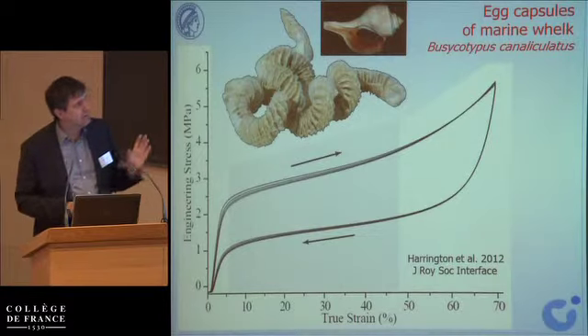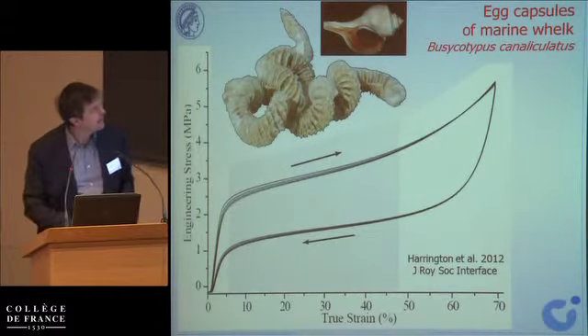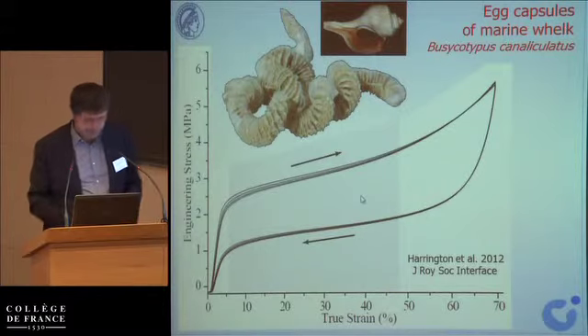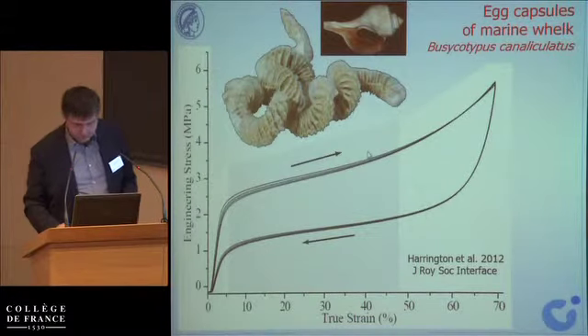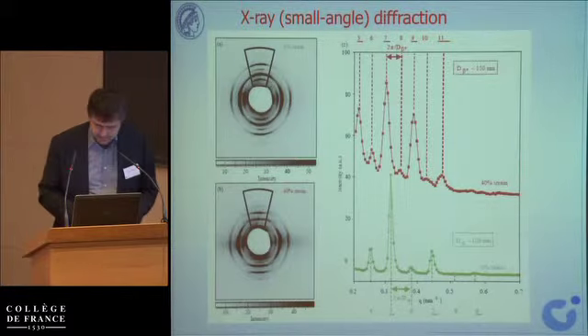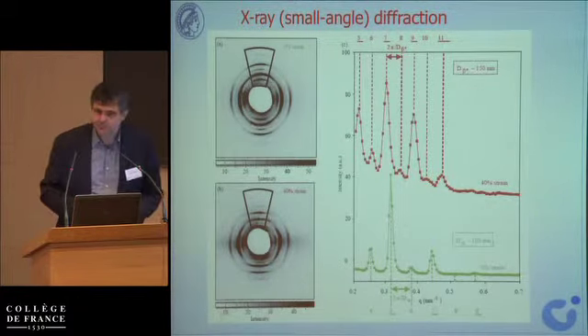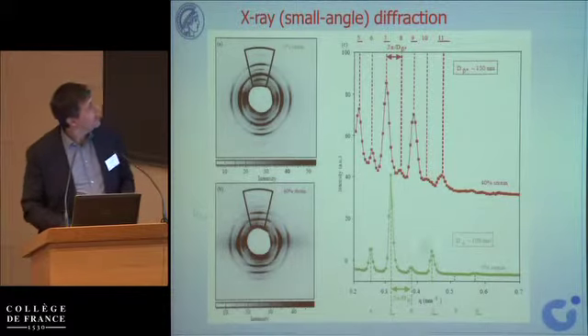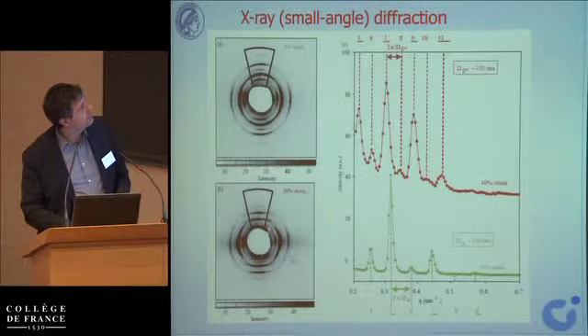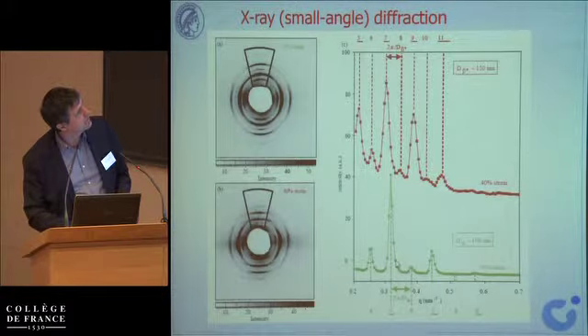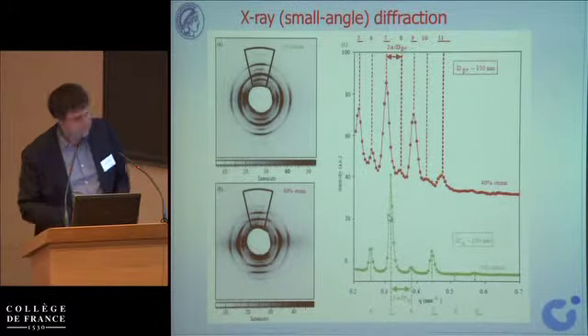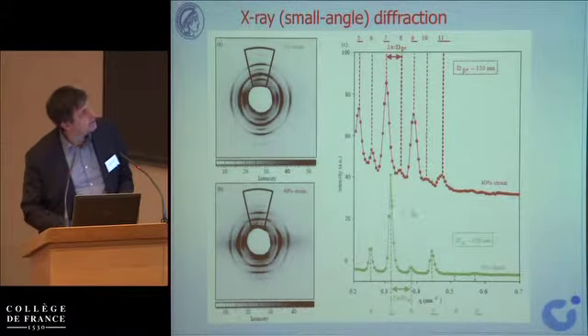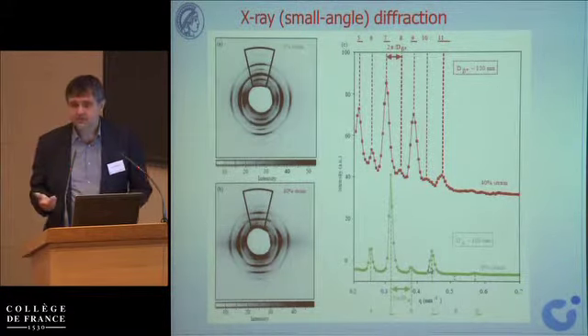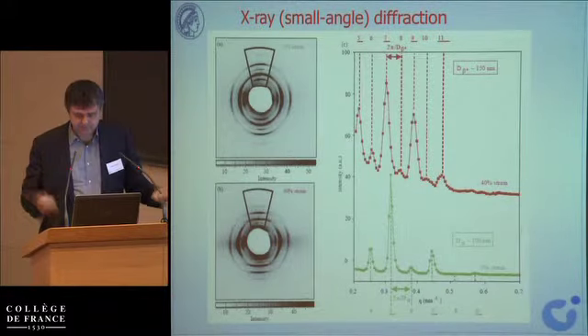Now a few comments about the other system. Now, how do you make something that's unchewable? So these are the properties. Now this is very interesting. Eve talked about phase change materials. So here is a phase change material. This is diffraction at 0% strain, diffraction at 40% strain. We just integrate this so they can see it better. So this is the red, this is the green. Not only did the peaks shift, which means that the protein is being stretched, but actually completely different peaks have appeared. So somehow this protein underwent a phase transformation.